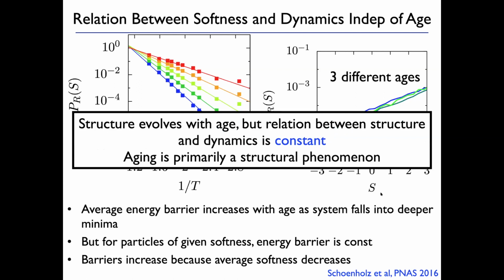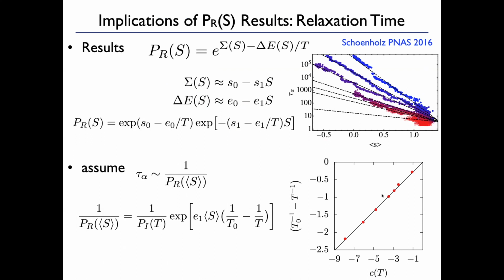So what that's saying is that what's happening with aging is that the structure is changing, but the relation between the structure and dynamics is the same. So aging is really a structural phenomenon. So if I do this, I can plot the relaxation time as a function of the average softness. And for different temperatures that I quench to, I get different dependencies. So the log of the relaxation time is approximately linear in the average softness, and for different temperatures that I quench to, I have different slopes, okay?